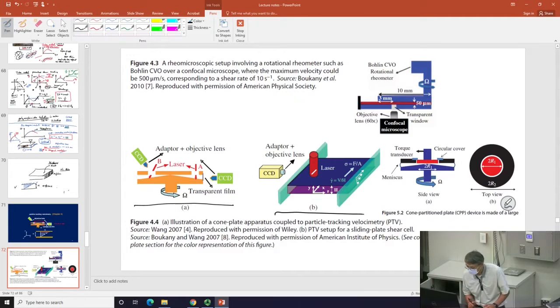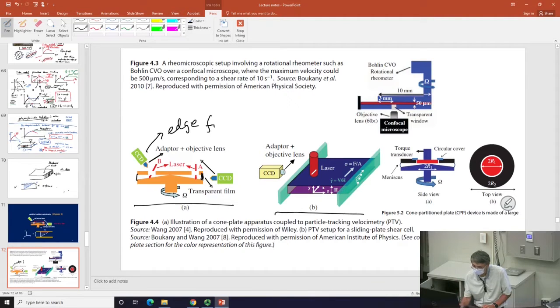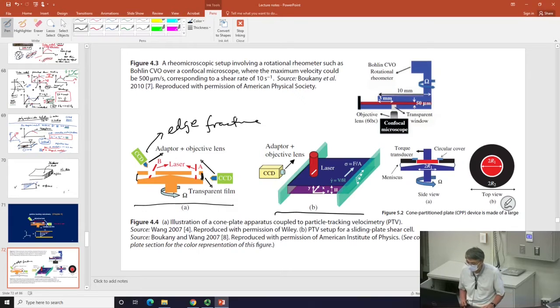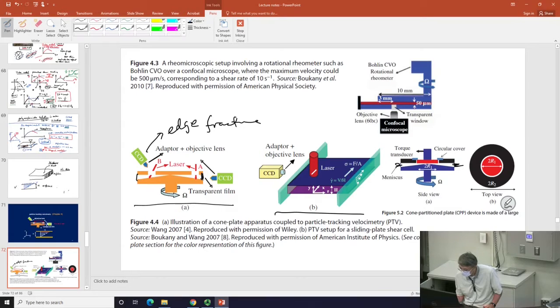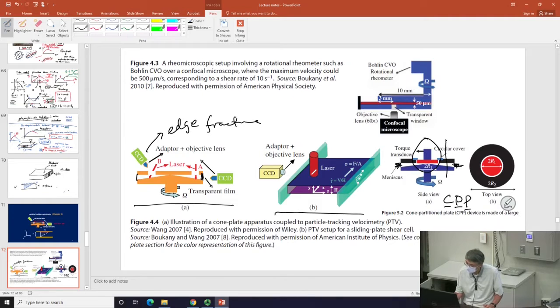In a cone plate case, you need to wrap a film; otherwise you cannot see inside. That wrapping of the film also prevents edge fracture. In general, you have a problem of the edge starting to misbehave, and the way to ensure this doesn't influence your measurement is by using the so-called CPP — cone partition plate — configuration. With this configuration you can also do particle tracking by shining a laser through and watching with a camera.